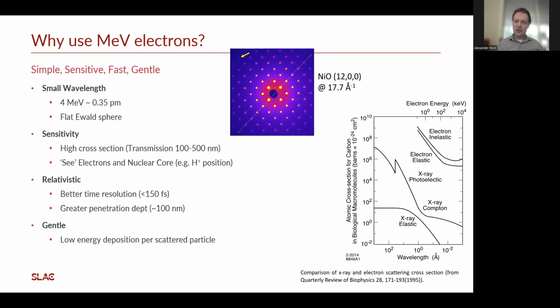This relativistic nature of the electrons also, when compared to, say, keV electrons that are more typically used in electron microscopy, does mean we have a slightly better penetration depth, or we can stay in a kinematic scattering regime for a lot thicker samples. And so for most of the sub 100 nanometer samples that we're measuring, we're staying more or less in this kinematic scattering regime.